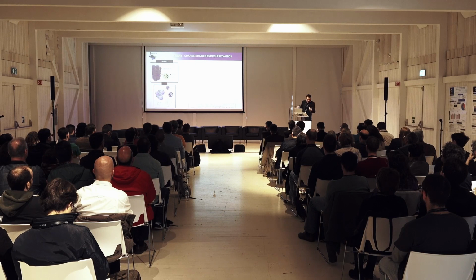Now let me dive into these different models describing each step of the manufacturing process, and the first one is the model simulating the slurry. Okay? So here we use an approach that we actually call coarse-grained particle dynamics. It's a kind of coarse-grained molecular dynamics at the particle level. Okay? Here, we define two types of particles, the active material and also aggregates between carbon, binder, and solvent. Okay?